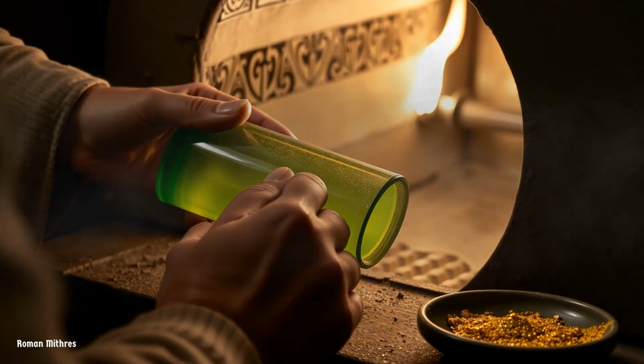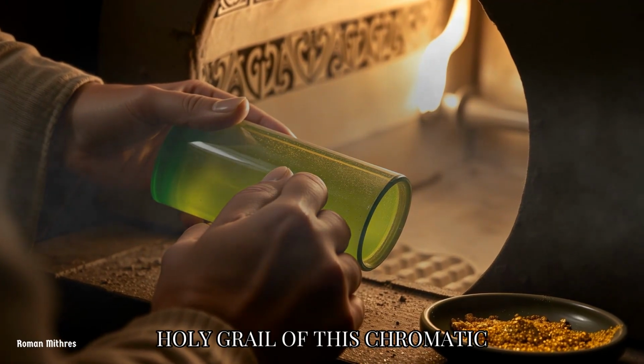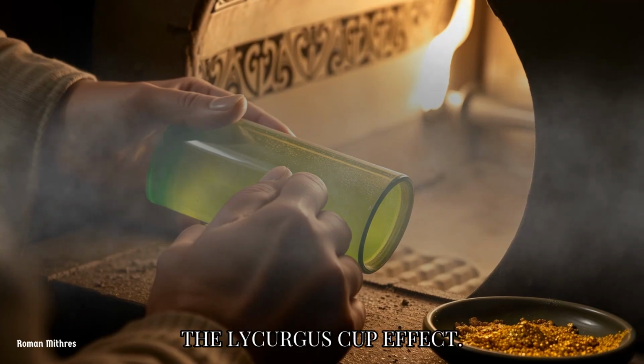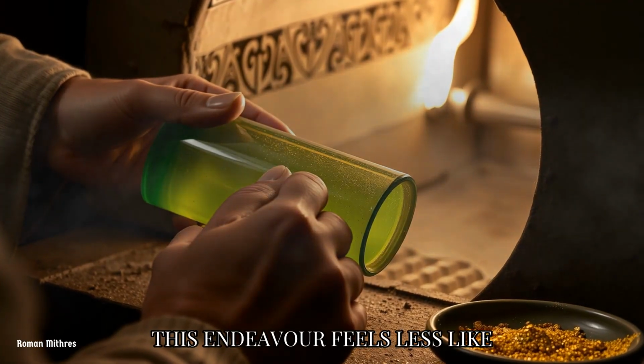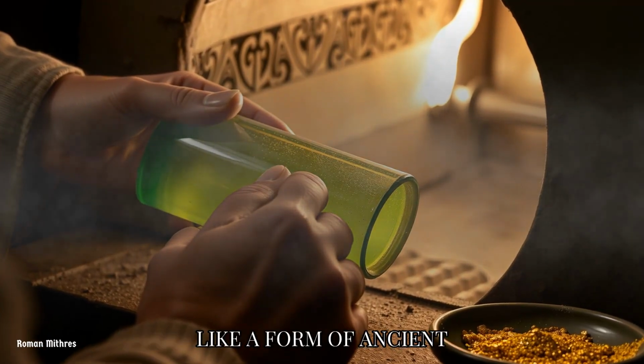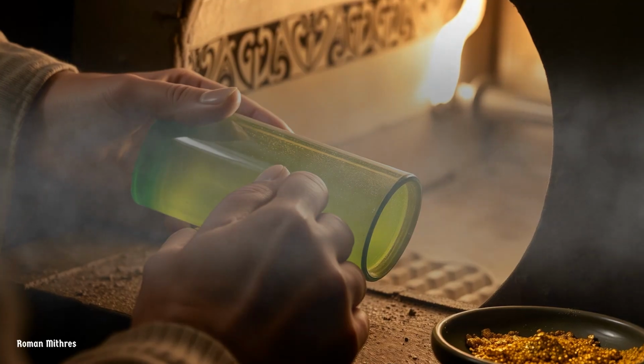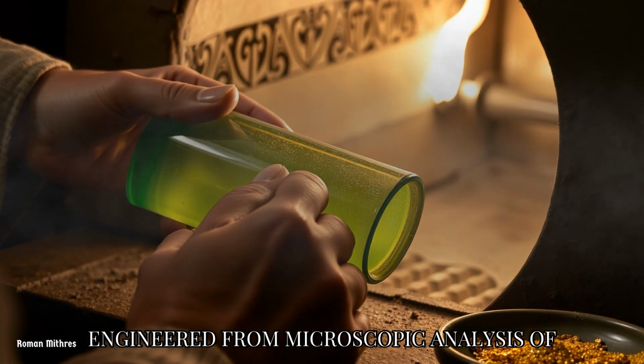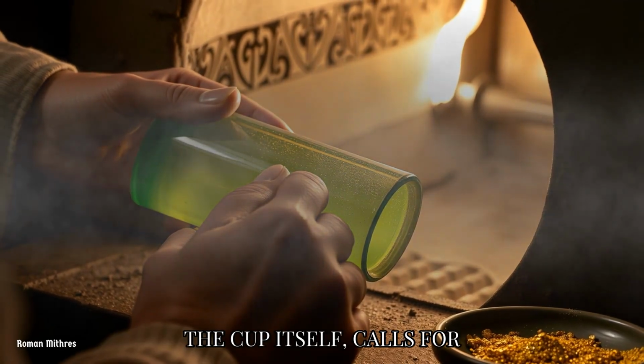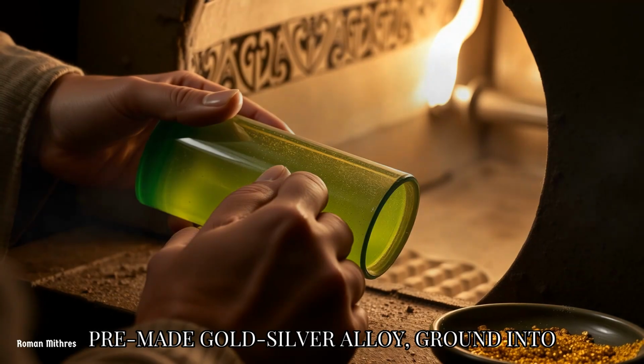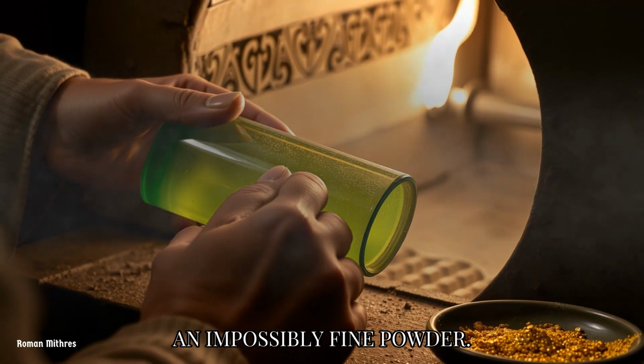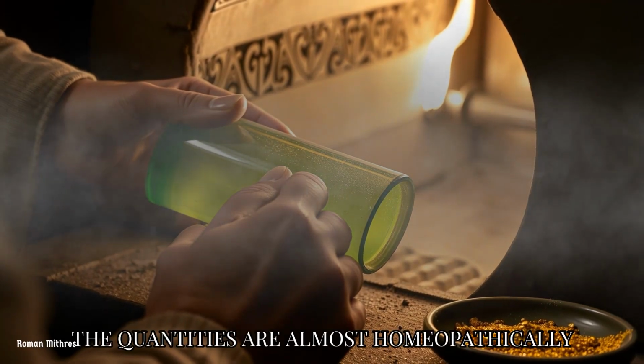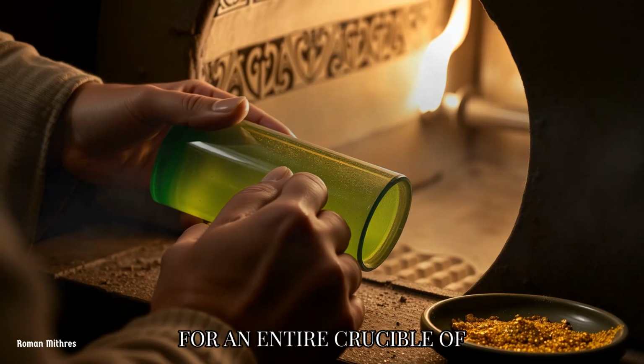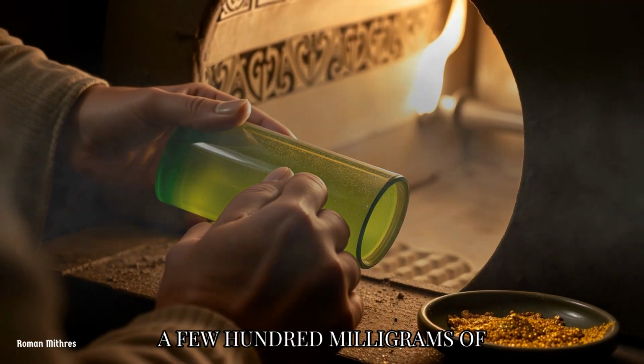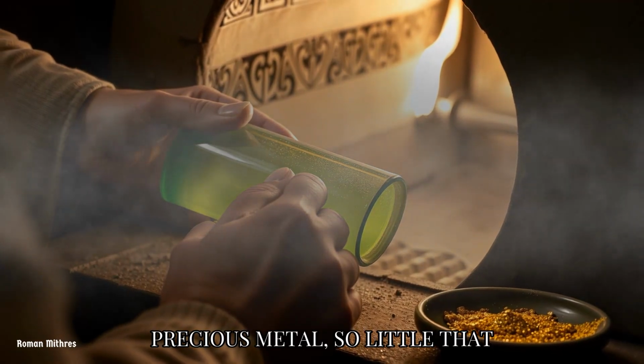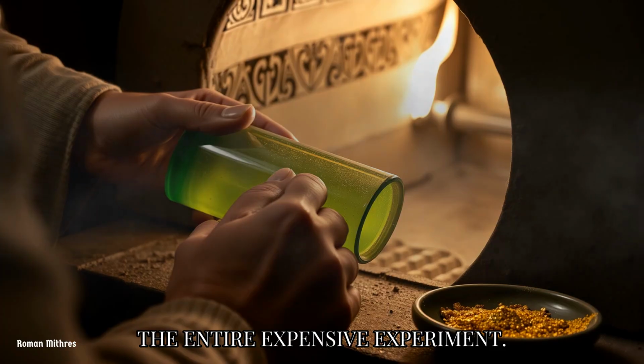Getting this transition exactly right is a high-wire act of fire management, a skill that clearly separated the Roman masters from the apprentices. But the ultimate goal, the holy grail of this chromatic quest, is the recreation of the Lycurgus Cup effect. This endeavor feels less like traditional glassmaking and more like a form of ancient nanotechnology. The modern recipe, painstakingly reverse-engineered from microscopic analysis of the cup itself, calls for a minuscule amount of a pre-made gold-silver alloy, ground into an impossibly fine powder. The quantities are almost homeopathically small. For an entire crucible of glass, they might add only a few hundred milligrams of precious metal, so little that a single sneeze could ruin the entire expensive experiment.